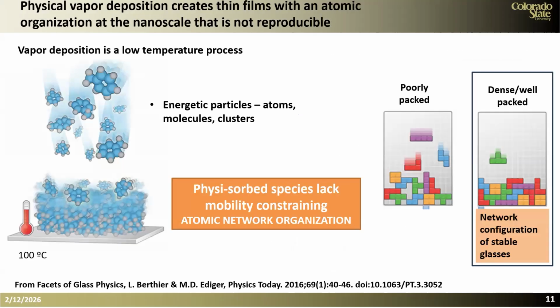However, the process that we use to grow these materials is physical vapor deposition, and this is a low temperature process. So this cartoon here shows that when the molecules and the atoms are dislodged from the target, they fall onto the substrate, which is typically at a temperature of about 100 degrees C. They stick to the place where they land and have very limited mobility. So as a result of this, it is very difficult to control the network organization in these materials.